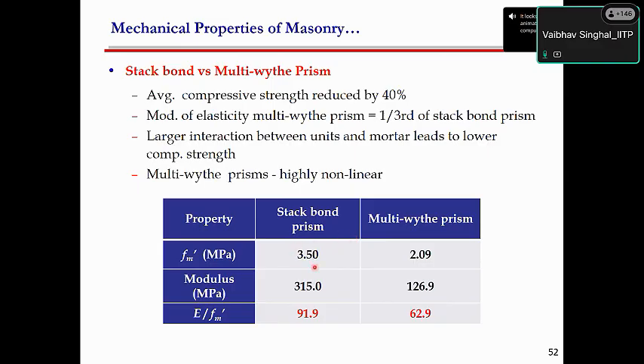For the masonry, the strength was 3.5 MPa. The modulus was quite low, 315. So it shows that the lime mortar provides high plasticity, or a low modulus, which is good. You can also say that is why these structures are still standing today. They were able to absorb various earthquake shaking. The multi-wythe prism, as expected, has a lower strength, 2.09 MPa, about 2.1 MPa, and also a lower modulus.